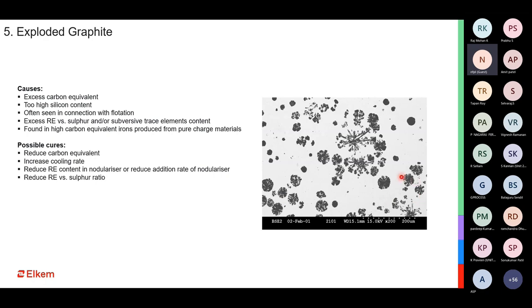If you look at it here, interestingly, all the graphite nodules which have exploded are large in size compared to the small ones, meaning that as the graphite becomes bigger, the tendency for explosion becomes higher. When we are having a higher carbon equivalent, meaning higher carbon and higher silicon, we often see this kind of defect. It is also connected to flotation. When you have more carbon coming out, you would have some amount of flotation happening.